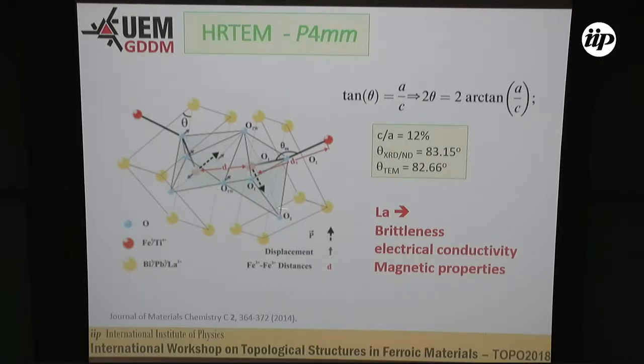If you see this image, you can do simple calculations. You see that this tetragonality factor is related to how these two octahedra of oxygen are pushed from one to the other. If you change this angle, for our calculations by using X-ray diffraction and neutron diffraction, this angle is 83.15. And by using our high-resolution transmission electron microscopy, this number is very close to another. And if you change the tetragonality factor, this interface can be stressed or not.